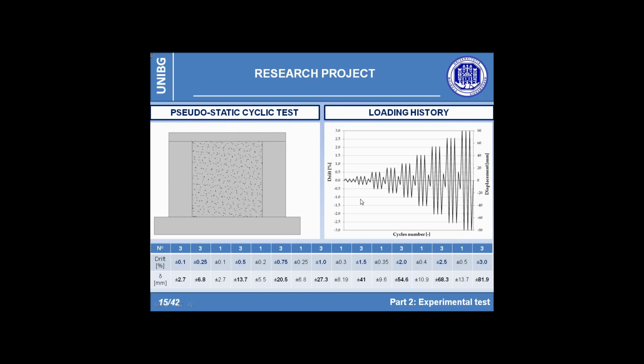All tests have been carried out by applying a cyclic displacement of increasing amplitude to the top beam according to the loading history shown in the table and depicted in the figure. The first level of the imposed drift, equal to 0.1%, is functional only to verify the elastic stiffness of the structure. After that, the loading history provides the execution of drift levels multiple of 0.25% until reaching the imposed drift coinciding with 1% of the story height.